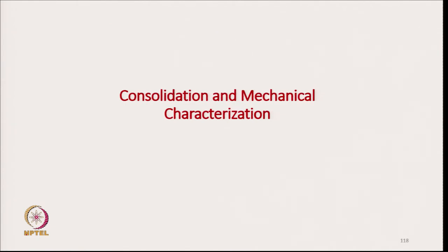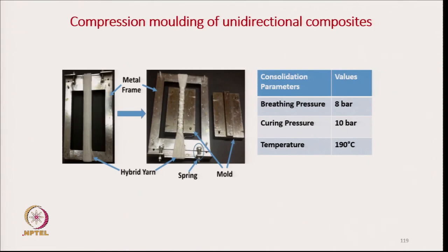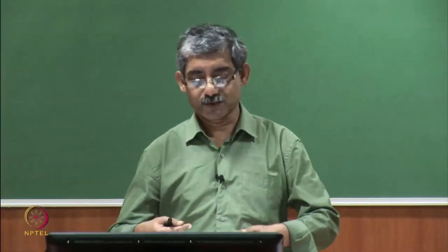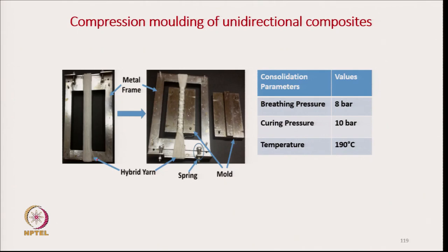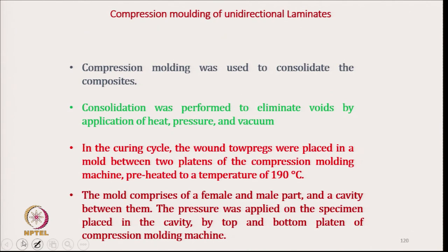Now the consolidation method and mechanical characterization. Here we have made the composite after wrapping a number of layers. The compression molding machine is used with a breathing pressure of 8 bar, curing pressure of 10 bar and curing temperature of 190 degree Celsius. These are the molds, male and female, pressed against each other, with the tow in between. So, compression molding was used to consolidate the composite.